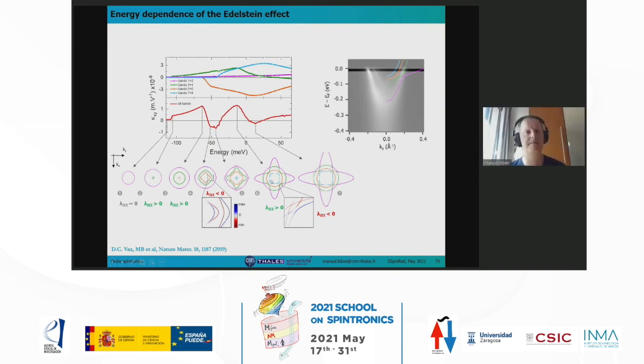Yes, actually, we published a paper with Ingrid Mertig and her colleagues a few months ago, about the orbital Edelstein effect. So just like here, I was talking about the spin Edelstein effect and inverse spin orbit Edelstein effect. You can have also the orbital Edelstein effect. So basically, if you wish, when you run a current, you will generate a transverse finite density of orbital angular momentum in addition to the generation of a finite density of spin. And the orbital to charge interconversion is much more efficient by a factor of 10 in our calculation. And I think this is a new domain which is starting now.